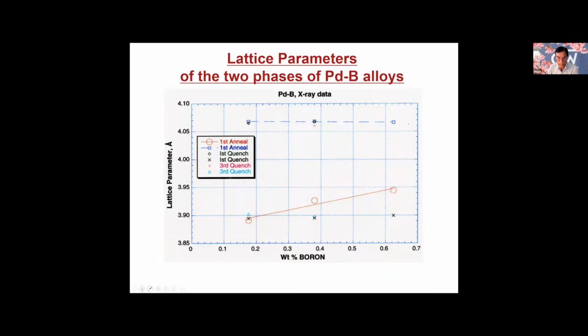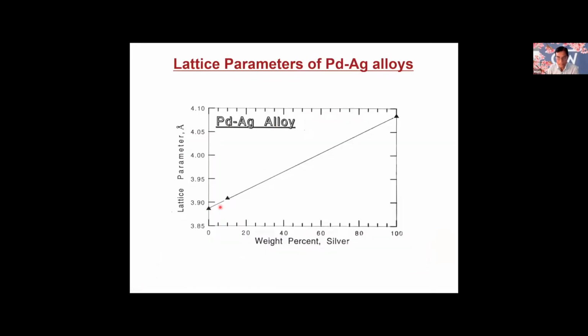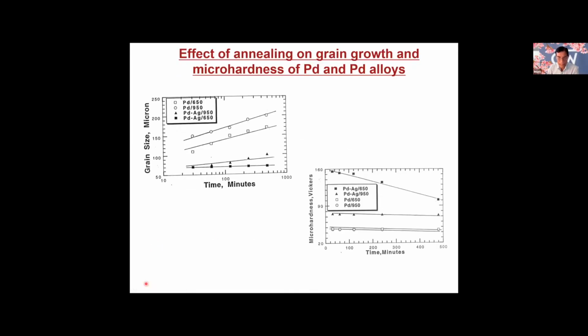And we looked at some silver, different types of alloys. So let me show you the palladium silver one. This is the palladium silver lattice parameter. If you increase the amount of silver, the lattice parameter increases, which is consistent with what we showed before. And this is just to give you an idea about what happens when you do some annealing. This is grain size here, this is time in minutes here. These are for the pure palladium, and this is 950 here, and this one here 950, and this is 650 here. And this is for palladium silver.